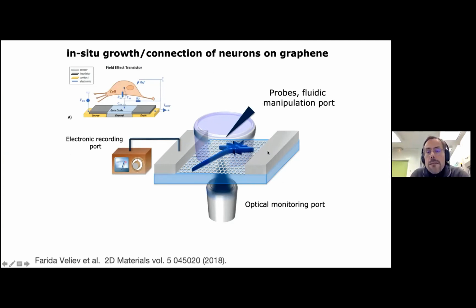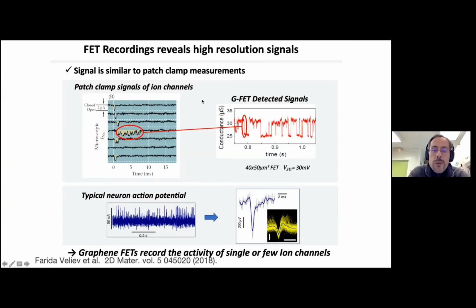and the in-plane to measure activity. So it's an extremely convenient setup you cannot make with silicon, for example, or with metallic layers. So that's why we use that in the beginning, and we published that in 2018. Interestingly, we found that we can detect a signal and that we could measure action potential and even intracellular potential due to the very specific interaction of pods of neurons with graphene.